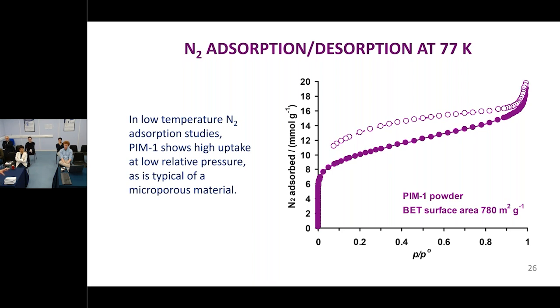There are some differences as well. You'll see if you desorb the nitrogen, it's not the same as what happens when you adsorb. That's a process of hysteresis. And it's not the same sort of hysteresis. If you have material with slightly larger pores, what are called mesopores, 2 to 50 nanometers, then you get hysteresis, but it always closes at a relative pressure above 0.4. And where it closes depends on the size. This extends down to the low pressure region. That's very typical of these sorts of materials.